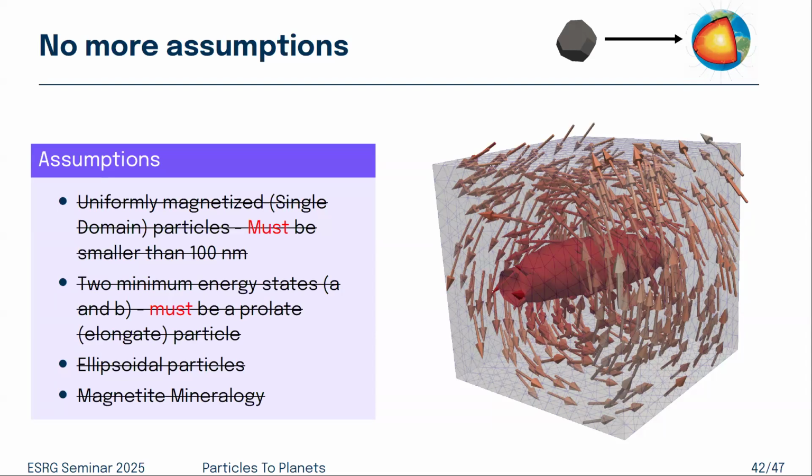Yeah. Are you thinking that actually, if you've got this whole spread of grain sizes in your whole rock, the stuff that you're seeing at tens of microns isn't carrying very much? That seems to be the case. I mean, there's a paper by Franco last year that seemed to suggest that the majority of remanence is being carried by particles in the 100 nanometers to a micron range. Okay, all right. So that does seem to be the case. Yeah.